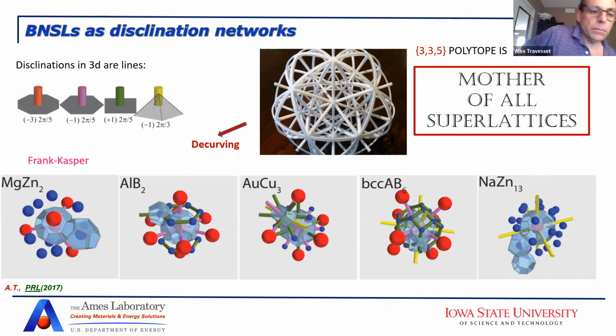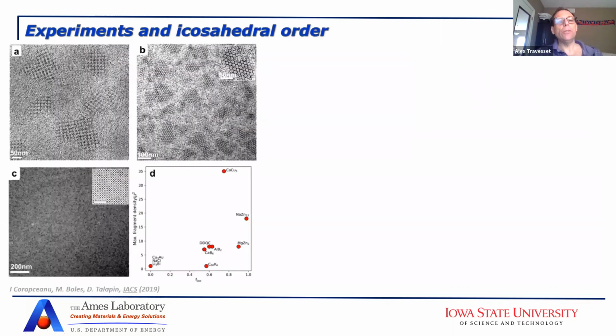So with that, I will mention a little bit of experimental evidence on that. What we were able to do is to assign a certain amount of icosahedral order to each superlattice. And then in the experiment, what they found is that the phases like sodium zinc 13 or calcium copper 5, which have a high level of icosahedral order, form very quickly, and they form small fragments very quickly, while those that have a very small amount of icosahedral order, like lithium-3 bismuth, form single crystals, which are very hard to nucleate.